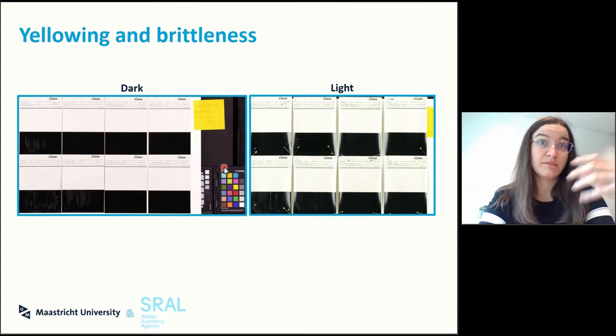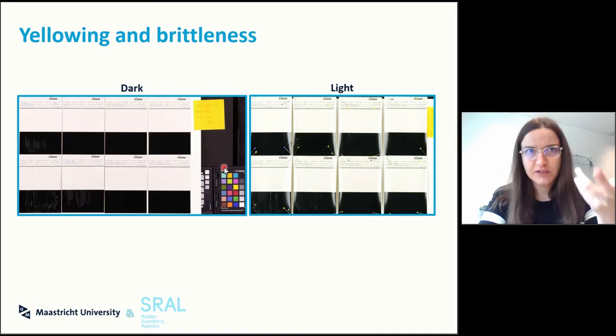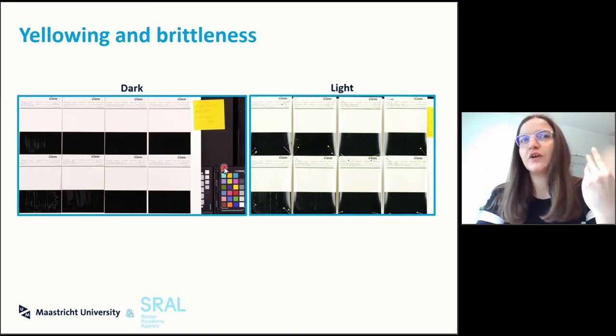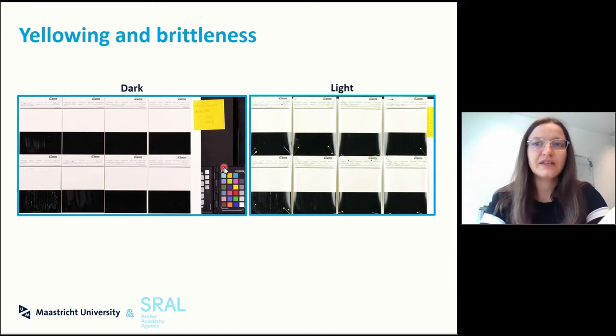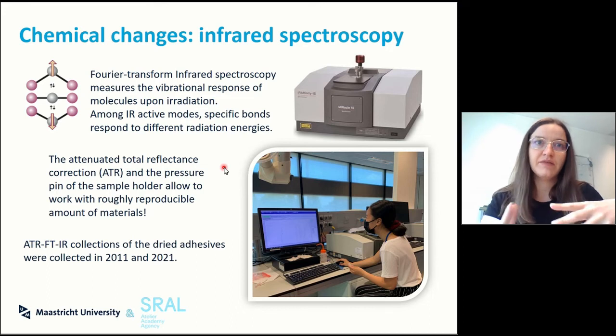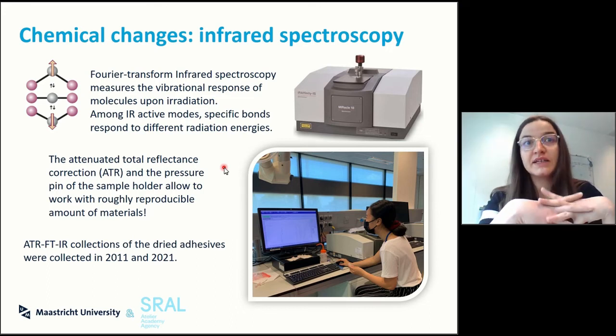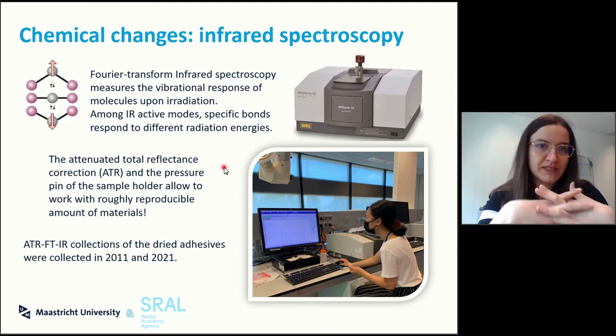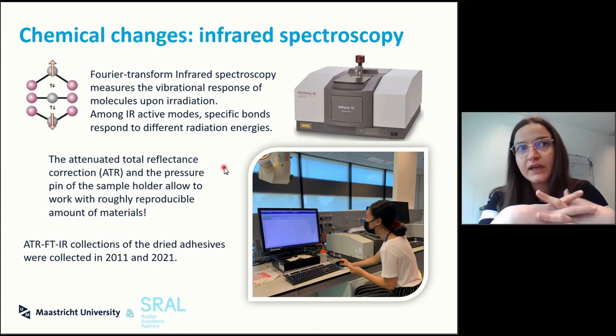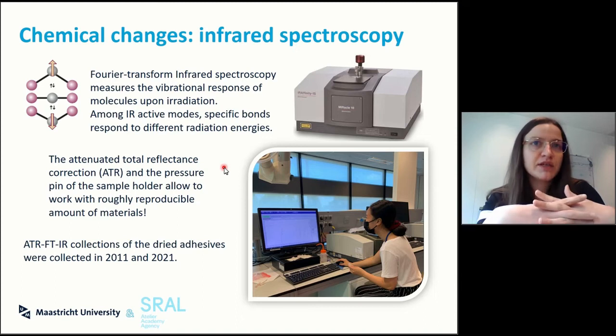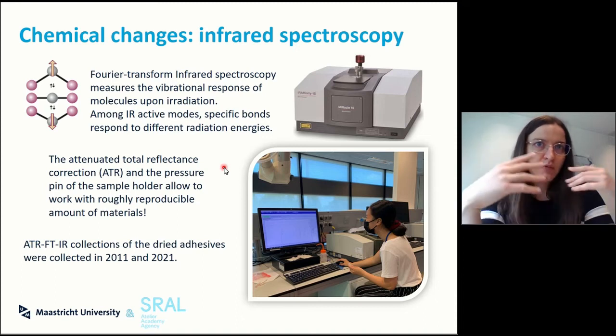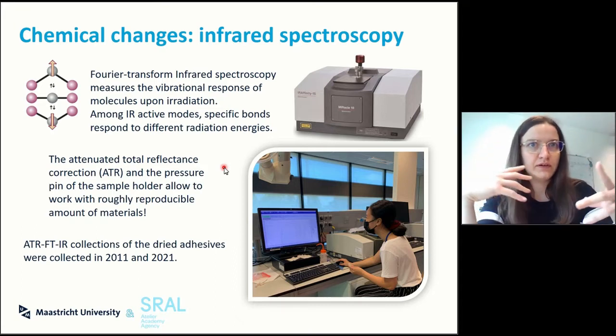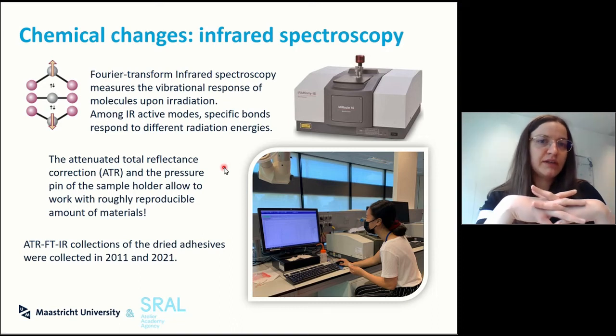So this gives you a way to see the macroscopical properties, but it doesn't actually give you an answer as to what is going on in the material, or if there is something about the substrate or something like that. So to actually test the adhesive as it was, we tested all the samples with infrared spectroscopy. Now, infrared spectroscopy is sensitive fundamentally to the bonds in your material. And every bond will respond differently, and given the tabulated frequency of the variation of the bonds against infrared light, we can have an estimation of what is active in the molecules. We used our instruments in attenuated total reflectance mode, meaning that this was suitable for use on an adhesive directly in the solid state.